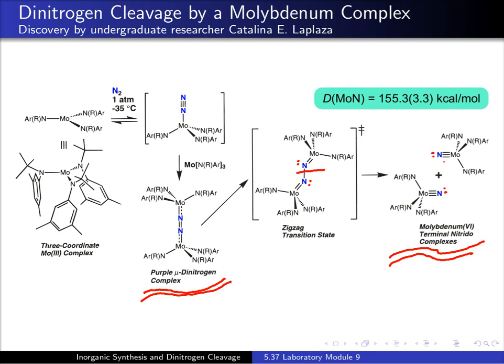We've been able to experimentally assess the metal-nitrogen triple bond energy, and its thermochemistry has revealed a bond dissociation energy for that linkage of about 155 kilocalories per mole. And we formed two of those very strong metal-nitrogen triple bonds in the course of cleaving the very strong bond of one N2 molecule, which is worth about 226 kcal per mole.